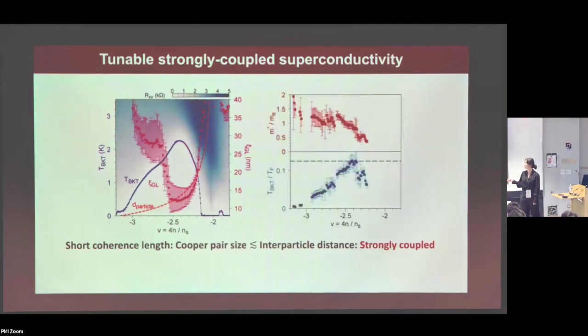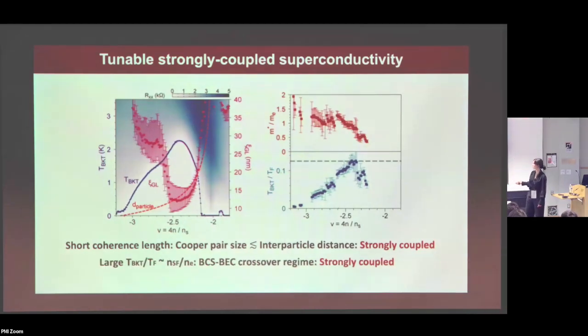Another evidence for the same kind of physics is that you can measure this quantity, TBKT, which you can for now just think of as the TC of the superconductivity, over TF, the Fermi temperature. That ratio, in simple terms, corresponds to the ratio of the superfluid density over the electron density. What this tells you is, among all your available electrons, or workers, how many of them contribute to the formation of Cooper pairs or superconductivity. And a value of over 0.1 for 2D superconductors is considered theoretically very high. So this is another evidence that we have very strongly coupled superconductivity that could be even very close to the BCS-BEC crossover regime.